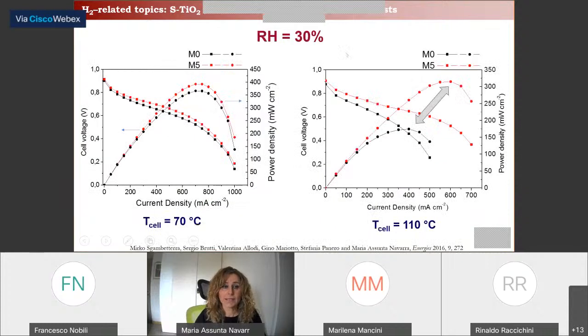Here I'm showing the results of the fuel cell test in terms of polarization and power density curves recorded under very critical low relative humidity of 30% and cell temperature increasing from 70 to 110 degrees. Compared to a plain Nafion membrane, shown here in black, our composite membrane containing 5% of sulfated titanium oxide really had better performance, especially when the temperature reaches the target critical higher value of 110 degrees. In this case, indeed, the composite membrane allowed higher current and power densities, probably thanks to its hygroscopicity and acidity properties.